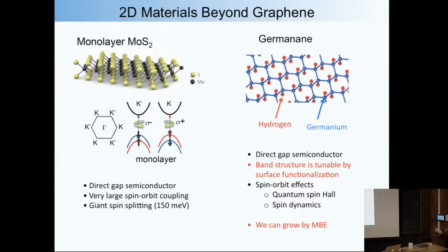And because germanium is heavier than carbon, you should expect to see spin orbit effects, like the quantum spin Hall effect. And because it's direct gap with spin orbit, you can study spin dynamics. And we're trying to do it also with alloys with silicon and tin, so you could change the amount of spin orbit coupling coming from the lattice. And the reason why I'm showing it to you is that this last point, we can grow this by MBE. I will show you. It's not perfect yet, but on germanium, basically.